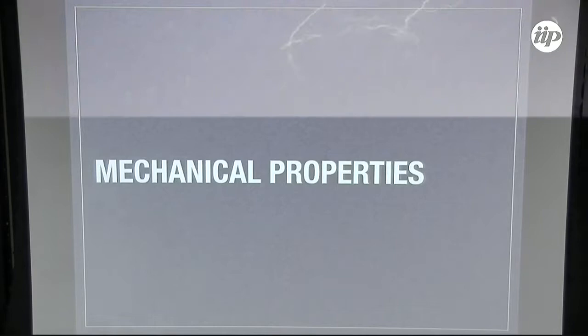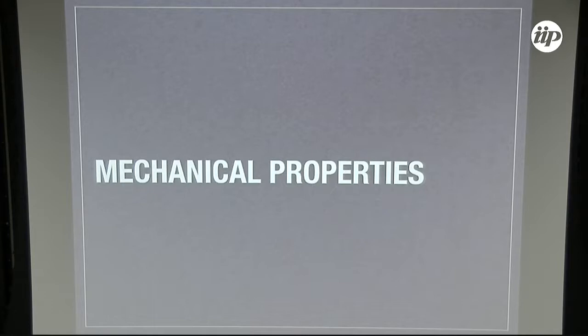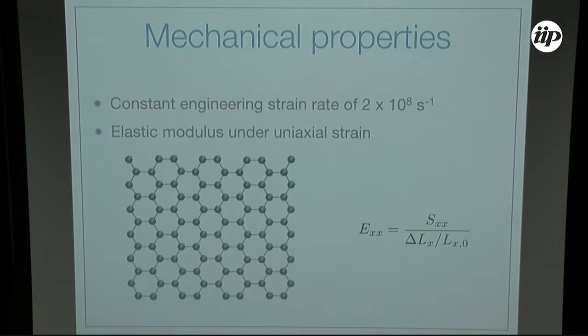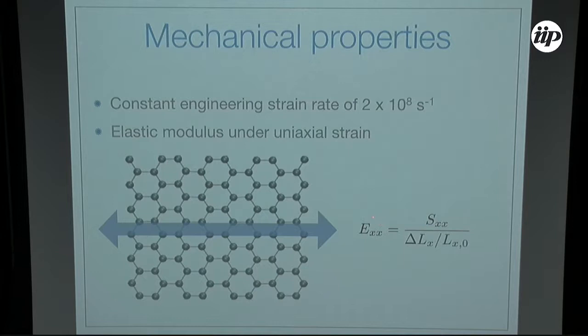What I want to do is look at mechanical properties and thermal transport properties with molecular dynamics — that's essentially the main tool. So I take a graphene sample, stretch it in one direction, and calculate the elastic modulus as the stress divided by the strain. I pull it at the rate of 2×10⁸ per second. Of course, in simulation it never gets to a second — it breaks much before that.